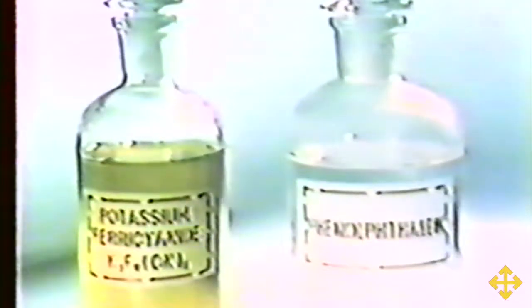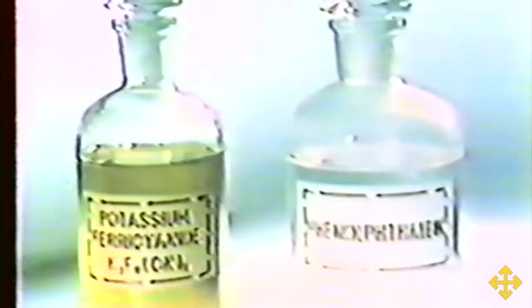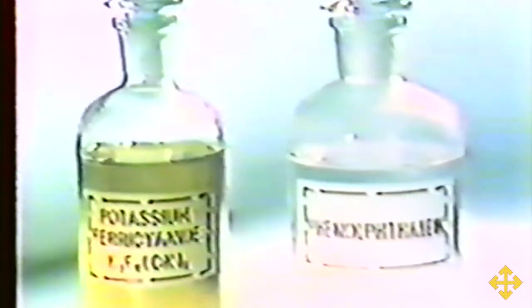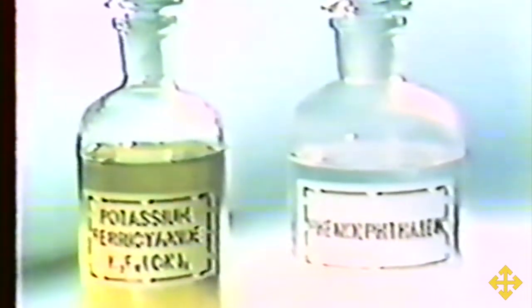The existence and location of anodes and cathodes in an oxygen concentration corrosion cell on a steel surface can be demonstrated by the changes in color of certain reagents as well as by the use of electrical instruments as in the preceding experiment. We have shown that the cathode reaction produces an increase in the concentration of hydroxyl ions as a result of removal of hydrogen ions or the reduction of oxygen. Phenolphthalein is a well-known indicator which develops a red color when the concentration of hydroxyl ions is increased to the point where the solution becomes alkaline.